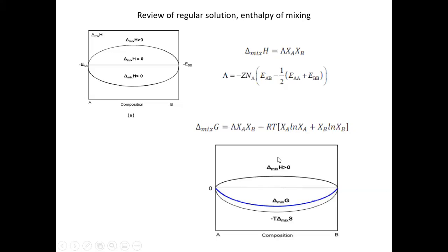But on the other hand, the enthalpy competes against this effect, meaning that from the energy point of view, the atoms do not want to be mixed together, because enthalpy increases if you mix them. If this is the case, you set up a competition between mixing and demixing, dominated respectively by the entropy of mixing and the enthalpy of mixing. The key parameter that determines which factor wins is the temperature. At a very low temperature, clearly I don't want to be mixed together, because I virtually have no contribution from the entropy. The only contribution is going to be from the enthalpy. So I don't want to mix, because this increases the free energy.